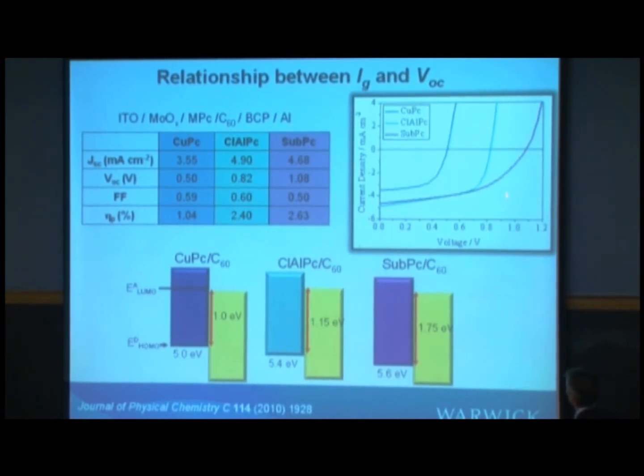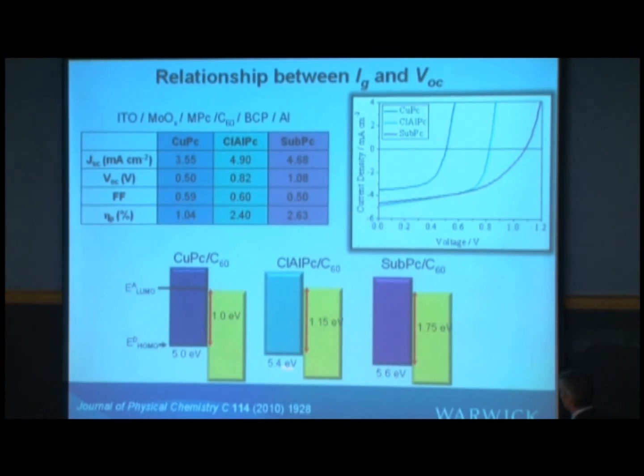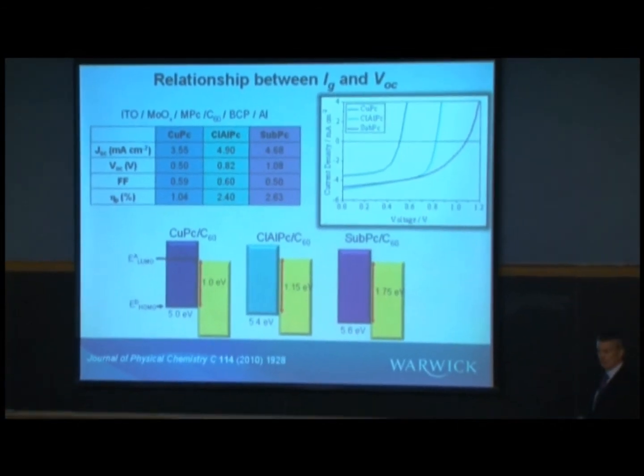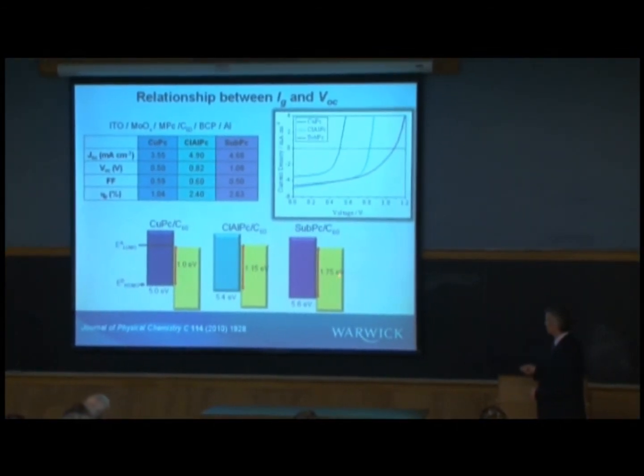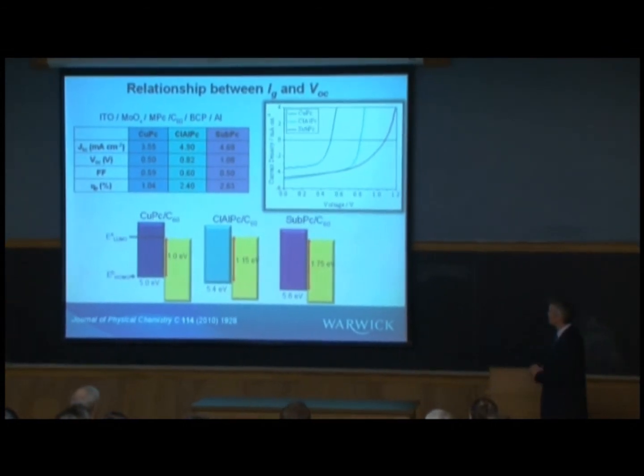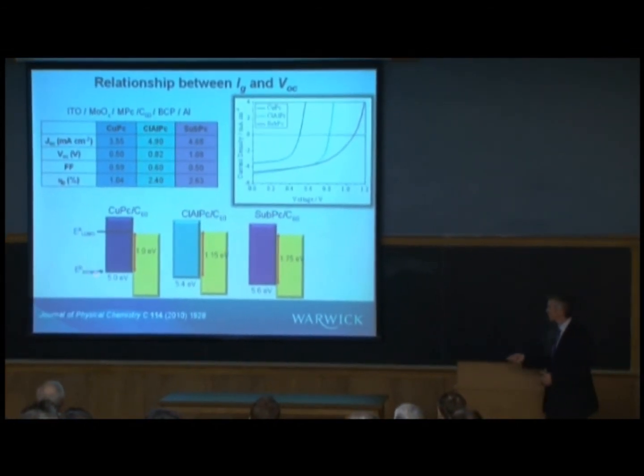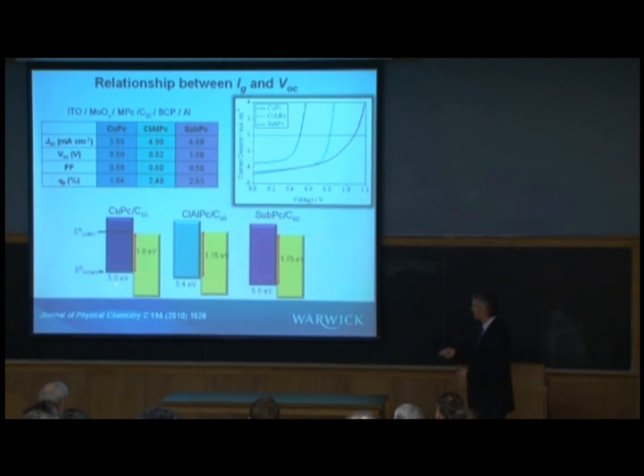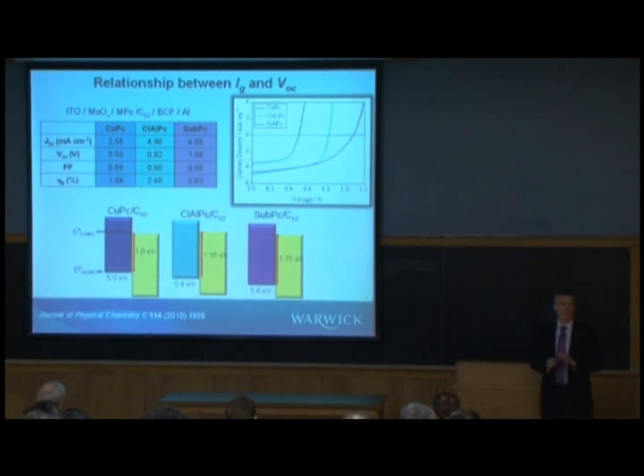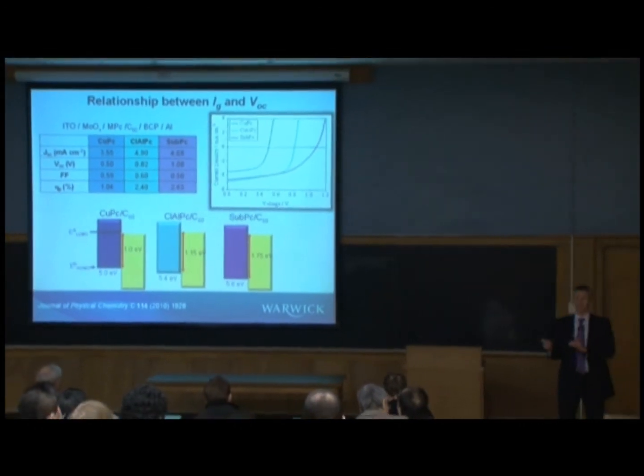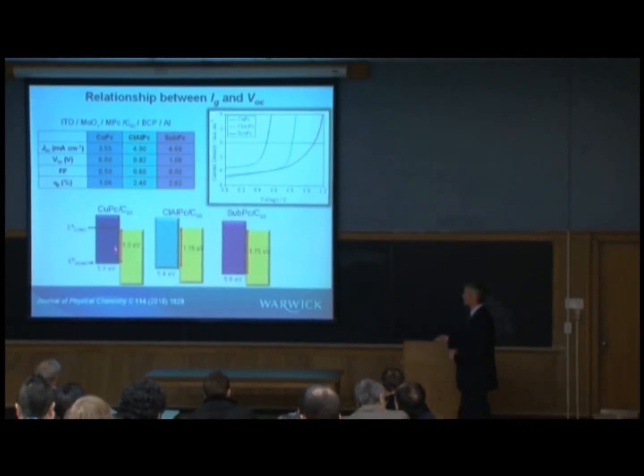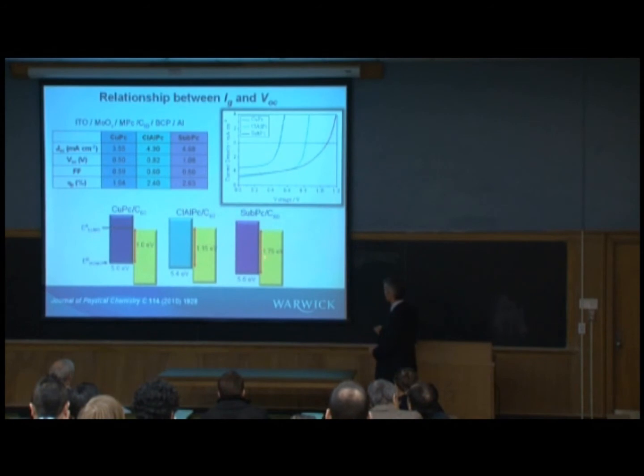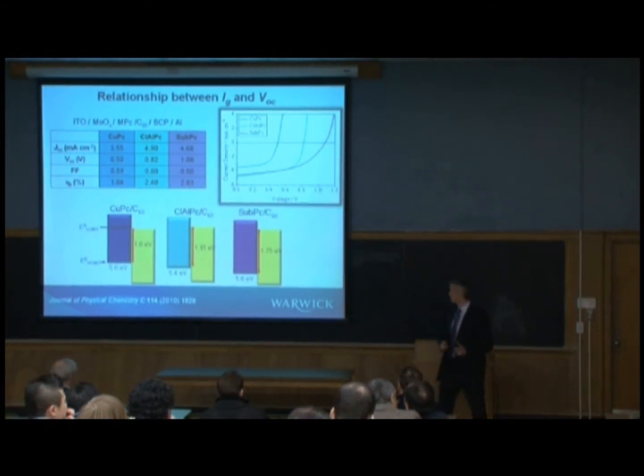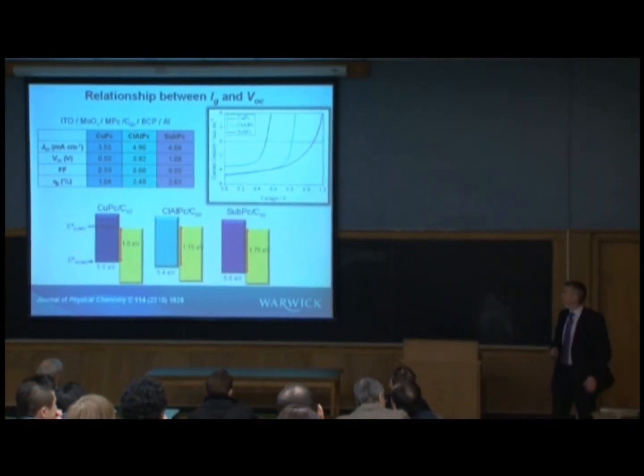These are the device results, the current voltage characteristics, and these are the schematics of the energy levels. Same acceptor, C60, different donors, different energy levels, so the HOMO goes down as you go from copper phthalocyanine to chloroaluminium phthalocyanine to subphthalocyanine, and the interface gap energy goes up. So for copper phthalocyanine C60, it's 1 eV. For subphthalocyanine C60, it's 1.75 electron volts.